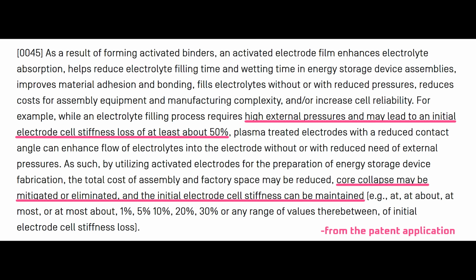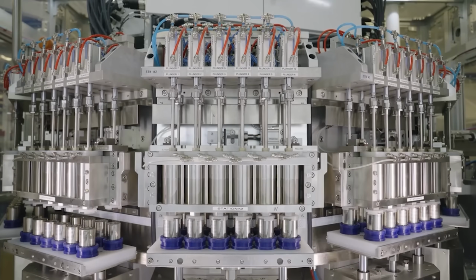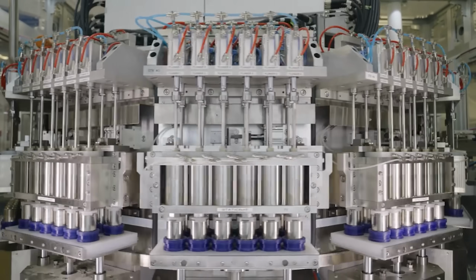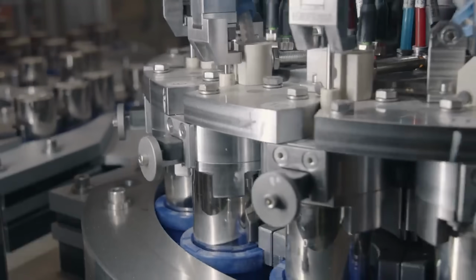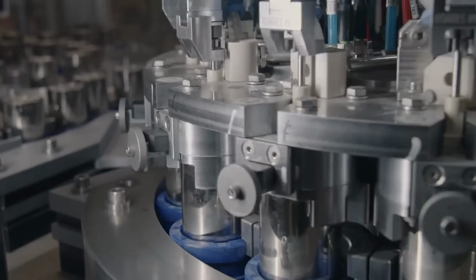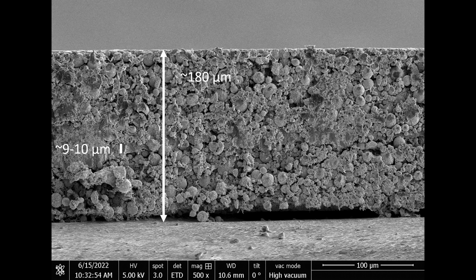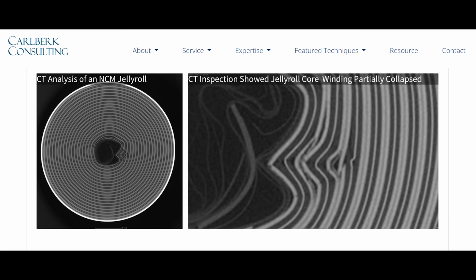Unfortunately, the patent application didn't precisely explain how plasma treatment solved the core collapse problem, but I have a few guesses. First, the sudden pressure changes caused by placing the cell under vacuum and then high pressure, which I'll call whiplash, could collapse pores in the electrode and separator, weakening them like balloons that have been inflated then deflated. That, in turn, is what might be causing the 50% reduction in stiffness.